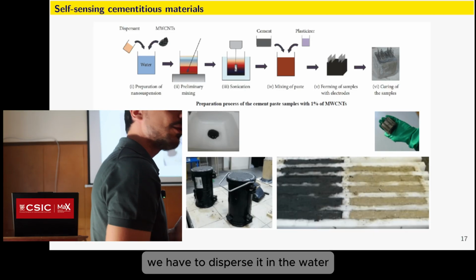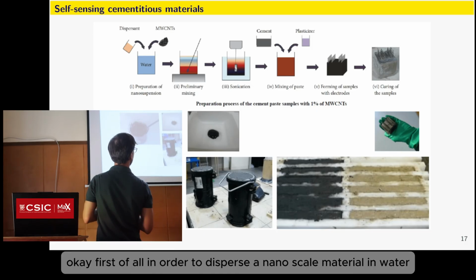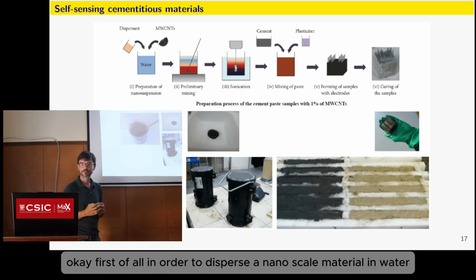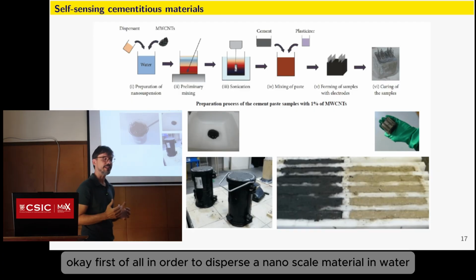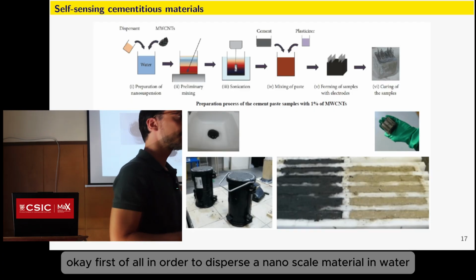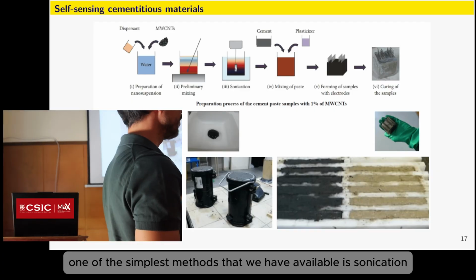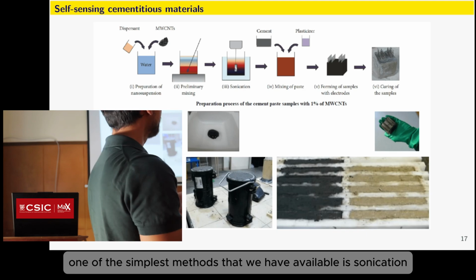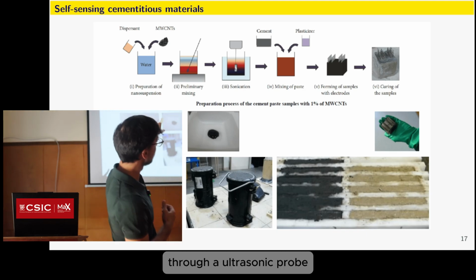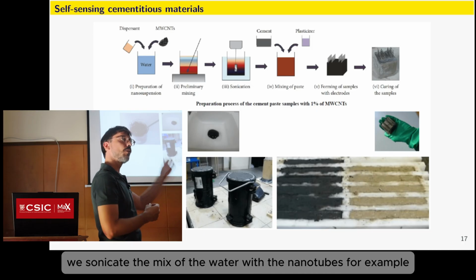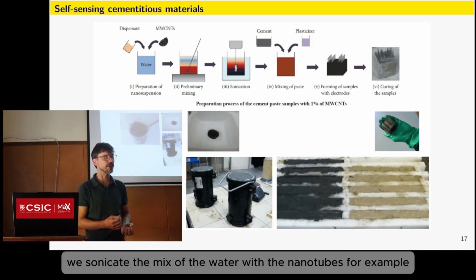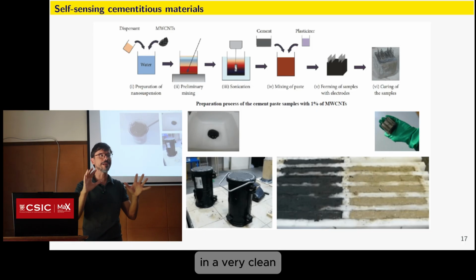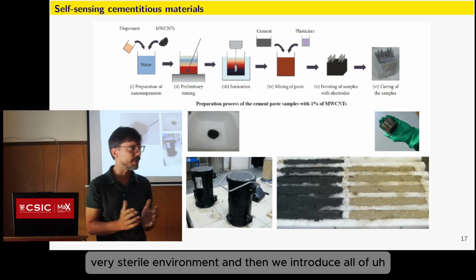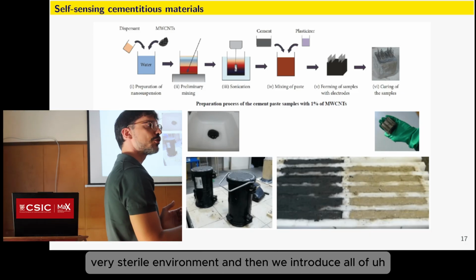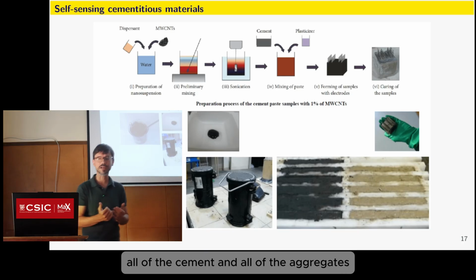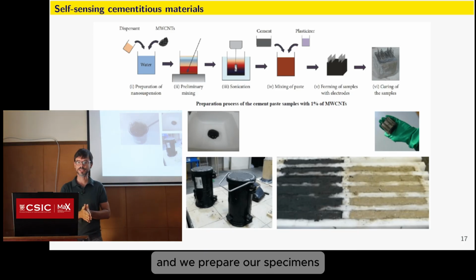We have to disperse it in the water. First of all, in order to disperse a nanoscale material in water, one of the simplest methods that we have available is sonication. Through an ultrasonic probe, we sonicate the mix of the water with the nanotubes, for example, in a very clean, very sterile environment. And then we introduce all of the cement and all of the aggregates, and we prepare our specimens.